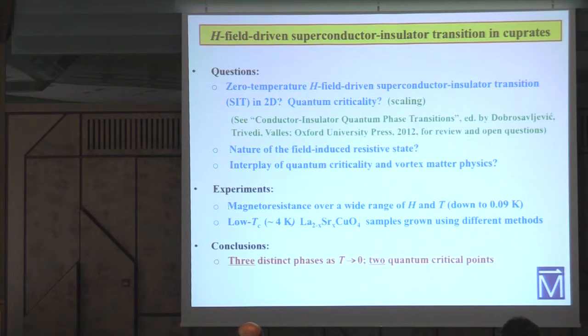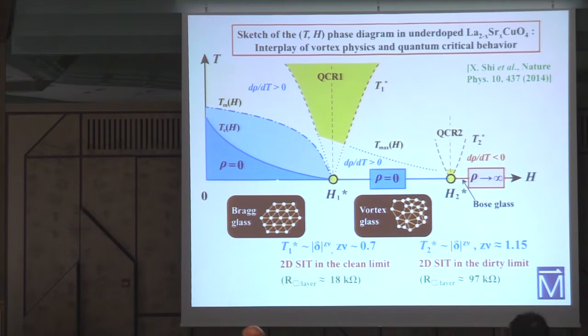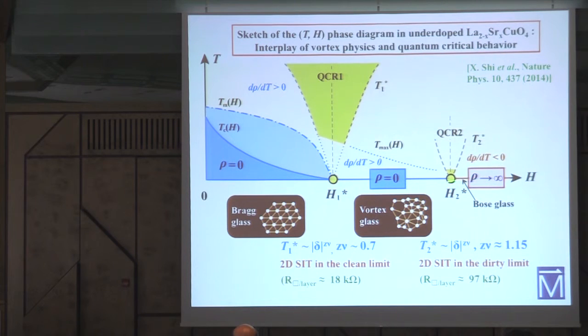We found evidence not just for one but for two quantum critical points with very nice scaling. We found evidence for two distinct superconducting phases: one where TC decreases with field and goes to zero at the first quantum critical point, and a second superconducting phase which is a superconductor only at zero temperature. At the second quantum critical point, we have a transition to the insulating state, where some superconducting fluctuations are still present. This transition is also consistent with the bosonic model for 2D superconductor-insulator transitions.